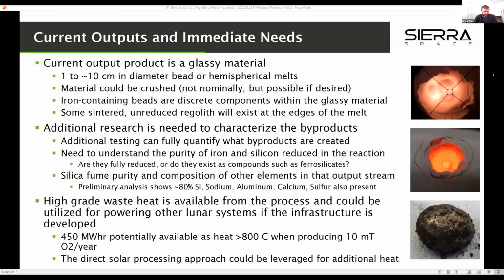The iron containing beads, as I showed, were discrete components. If you're processing mare material, those iron beads are a much larger size relative to the overall melt. So there's some advantage, and obviously there's a lot more iron there. And then there's also some sintered, unreduced regolith that exists at the edges of the melt. If you look at the photo on the right, you can see we use the regolith as its own insulating container, so we get around the material's compatibility and corrosive issues by doing that. Where I really think near-term additional research is needed, we need to quantify what the actual structure and composition is of those byproducts that we create.